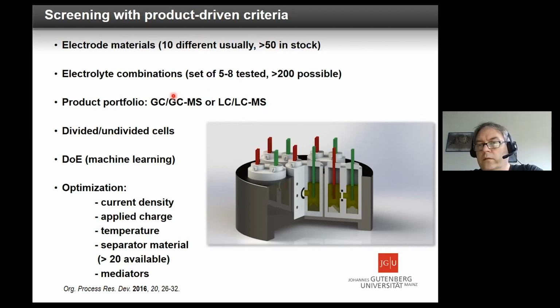With electrolyte, you can choose everything which is conductive. But the problem is we have to look earlier at that point already. First of all, it should enable the conversion, but it should have no environmental constraints and no safety issues. And of course, the costs are also an argument. Therefore, we have usually 5 to 8 which do the job, but around 200 which are usually feasible. We directly look into the system if the product is accumulated or not by GC or by LC, and couple this with mass spectrometry. This is the divided cell, but also the undivided cell.